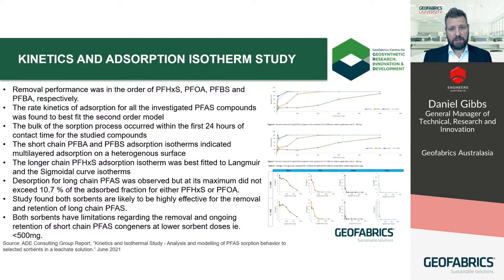The short-chain adsorption isotherms indicated multi-layer adsorption or stacked adsorption, which can result in higher desorption levels or easier desorption under certain conditions. Long-chain desorption was lower or better than short chains. Both sorbents were very effective at trapping the long chains, but at low doses were less effective with the shorter chains. But still, even at 0.5 gram addition rate, even the more difficult PFBA achieved around 80% removal. Naturally, a change in solution chemistry may affect this for the better or worse, which is why targeted compatibility assessments are always recommended prior to product selection.